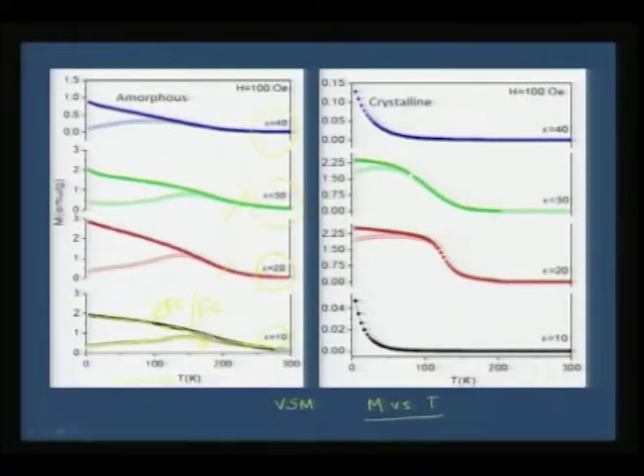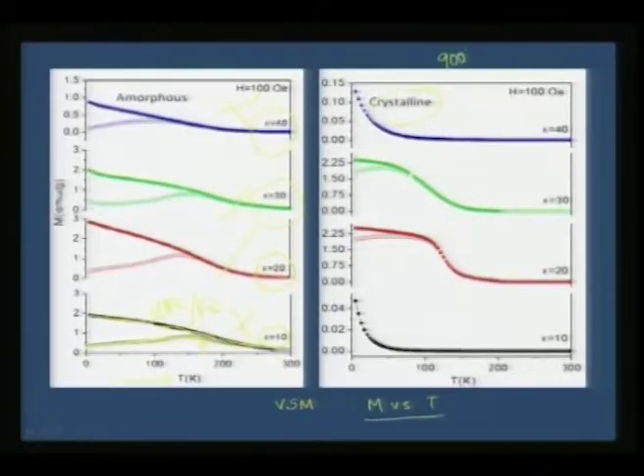If you quickly remember the equilibrium phase diagram that we saw, these two regions are supposed to be magnetic according to the phase diagram, whereas these two are not supposed to be magnetic. But irrespective of that, in amorphous phase all the compositions are turning magnetic, whereas if you look at the crystalline phase, which is the 900 degree sintered samples, when you do the M versus T curve, you can clearly see that the x is equal to 10 and x is equal to 40, they are immediately turning non-magnetic. So, this is according to the equilibrium phase diagram, whereas in this case we see it is against the prediction of the equilibrium phase diagram.